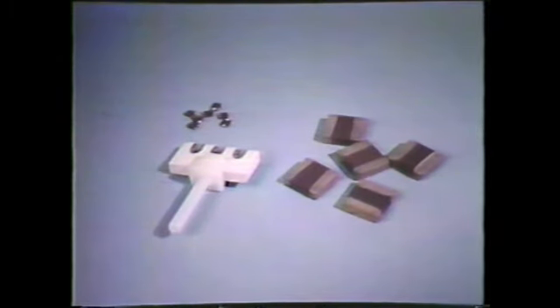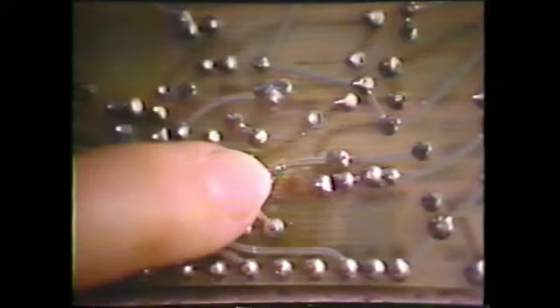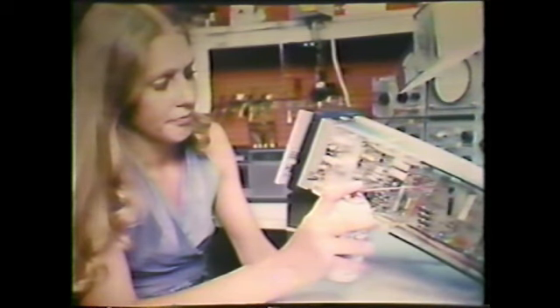Use extra care when soldering wires. Melted insulation, nicked wires, and loose strands are unacceptable. Chip parts and other special parts may require a special type of solder. All flux is corrosive and must be removed. Use only approved solvents. Don't use Freon solvent. Circuit coolers can damage temperature or static sensitive parts. Never use a Freon cooler.